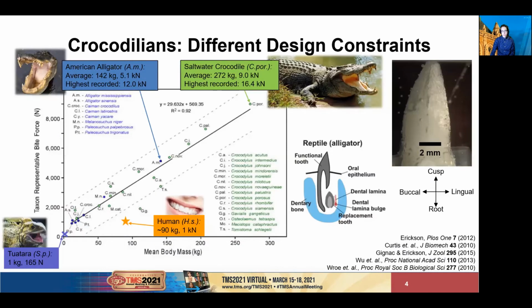The most distinguishing characteristic of crocodilians is they have drastically higher bite forces than humans. This graph from Erickson shows the representative bite force as a function of mean body mass for all 23 extant species of crocodilians. The saltwater crocodile here has the highest recorded bite force of any living terrestrial animal at 16.4 kilonewtons, though the average is closer to 9. American alligators have an average bite force of 5.1 kilonewtons, and for reference, humans are generally in the neighborhood of 1 kilonewton.